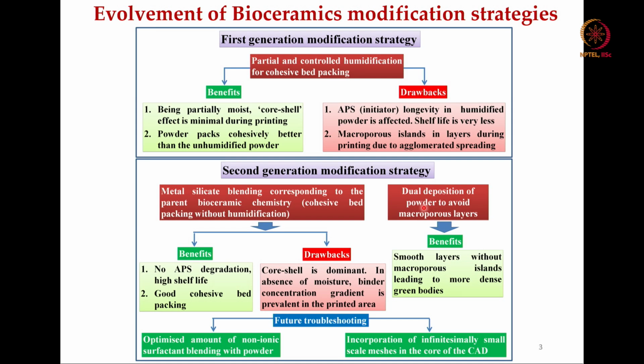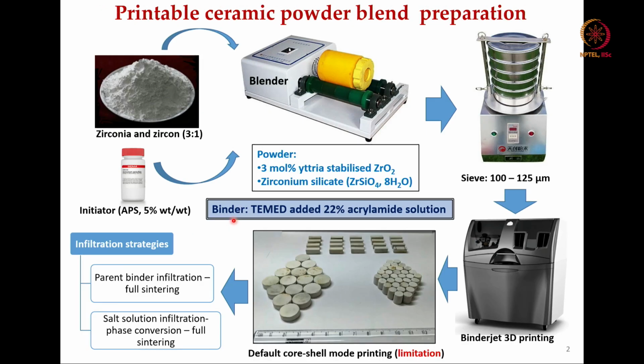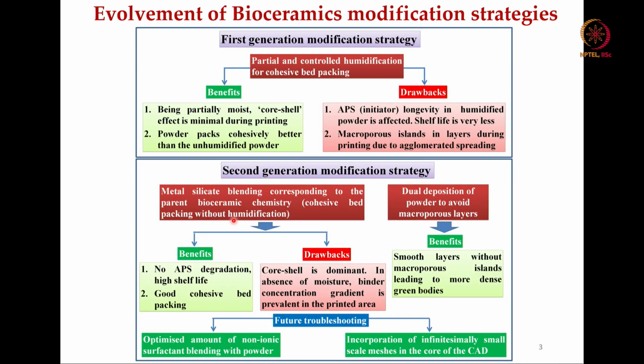This is a little busy slide. Let me go through it slowly. So, these are the bioceramics modification strategies. The first generation strategy is essentially partial and controlled humidification for cohesive bed packing. What are the benefits? When the powders are partially moist, the core shell effect is minimal, and some of the powder packs cohesively better than the unmodified powder. However, the shelf life of the APS initiator is very short, and there are macroporous islands, that is what we found. Now, the second generation modification is metal silicate blending corresponding to the parent bioceramic chemistry, like zirconium silicate ZrSiO4 8H2O being blended. There is no APS degradation and good cohesive bed packing has been observed.